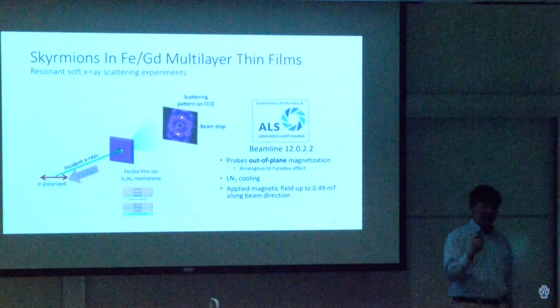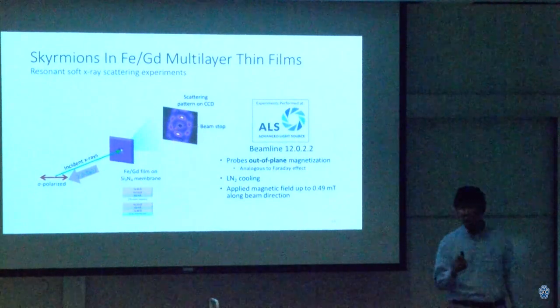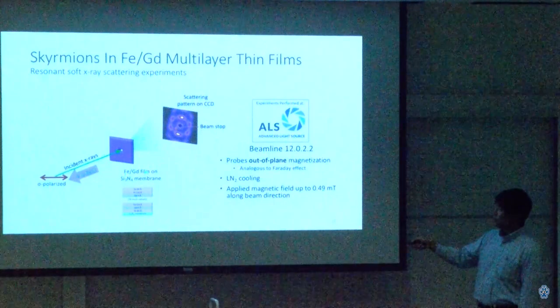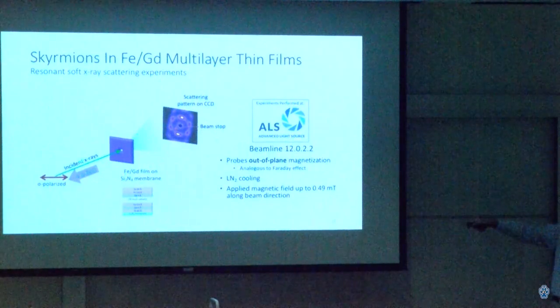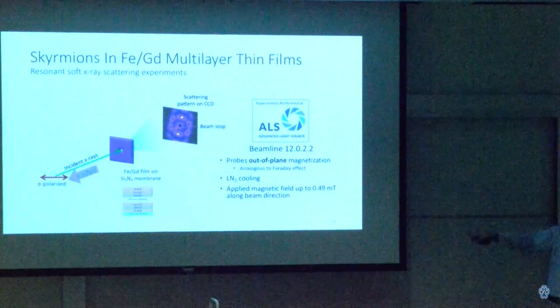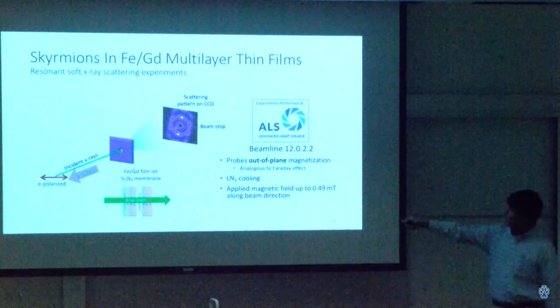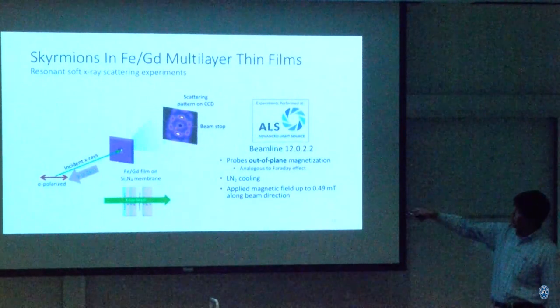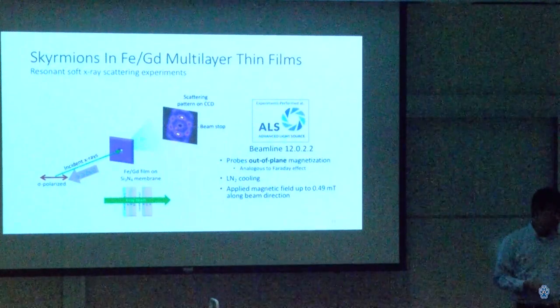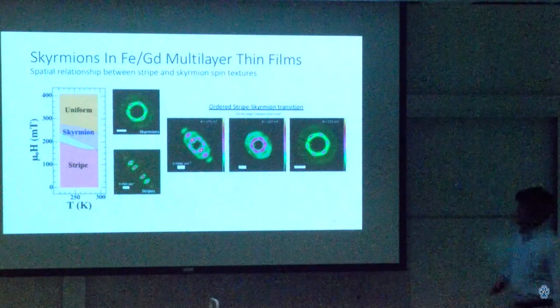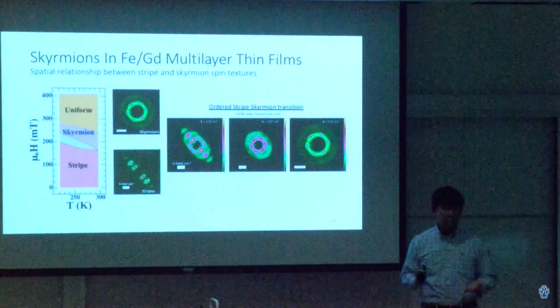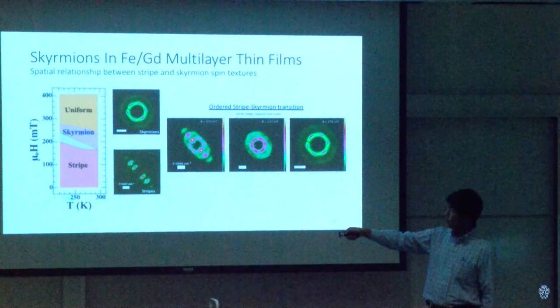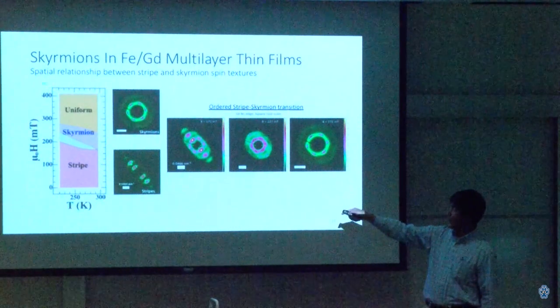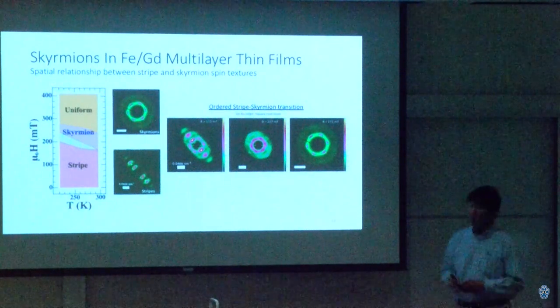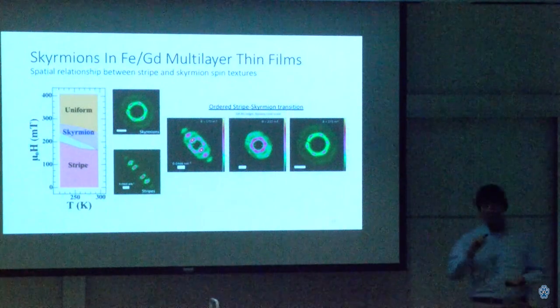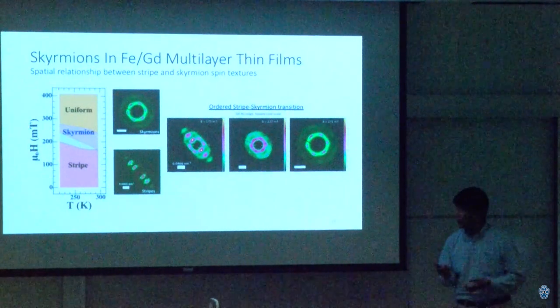And the idea is we can tune the energy or the wavelength of those X-rays in order to probe the magnetic state of either iron or gadolinium. Tuning the energy for, say, iron and gadolinium and sending the X-ray beam through causes a diffraction pattern to be captured downstream of the beam onto a CCD camera. We change the temperature of the sample as well as the applied magnetic field. That's what's on the horizontal temperature and vertical axis of this phase diagram. And we saw the magnetic texture change via changes in the X-ray diffraction pattern.